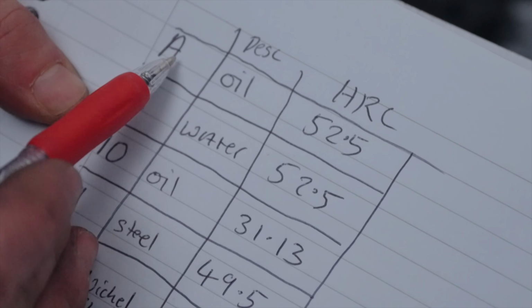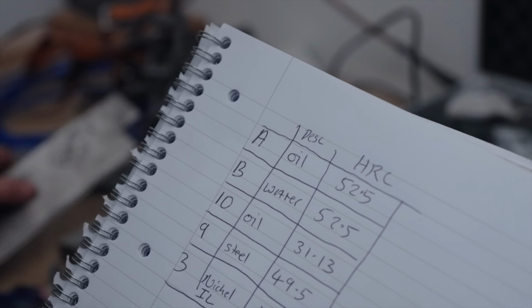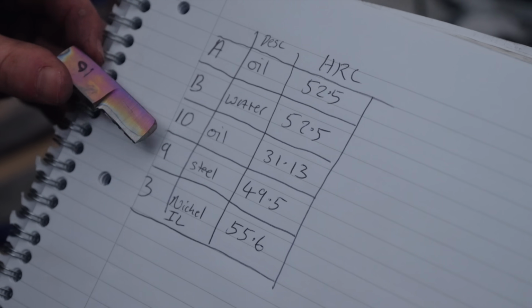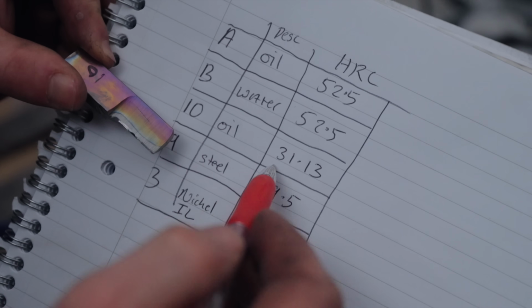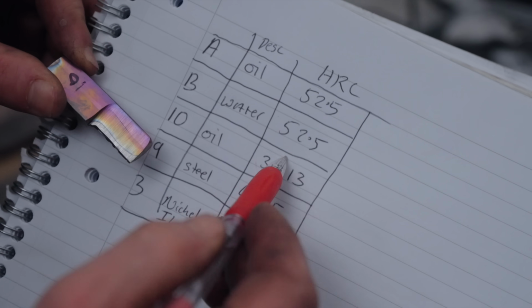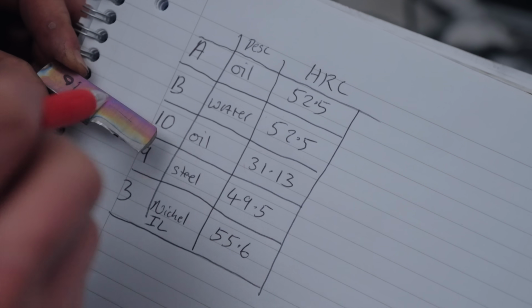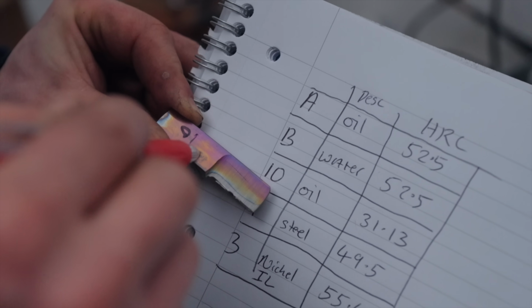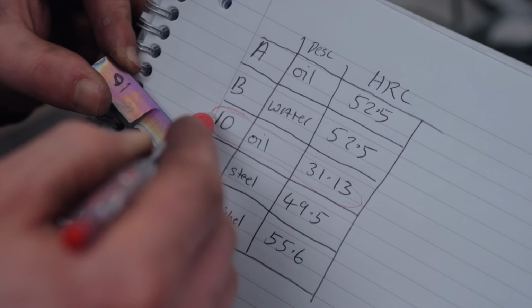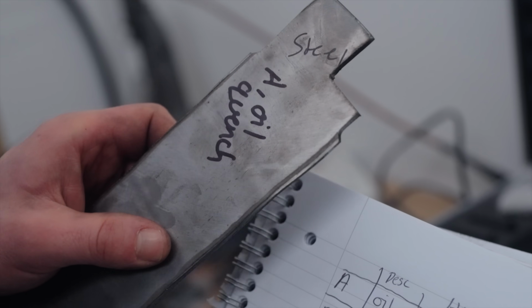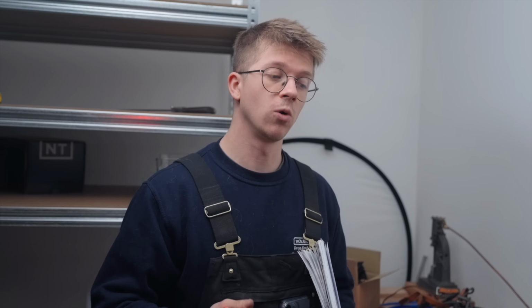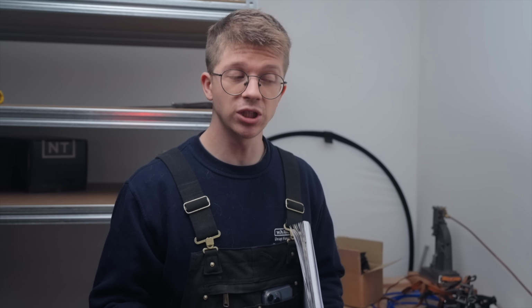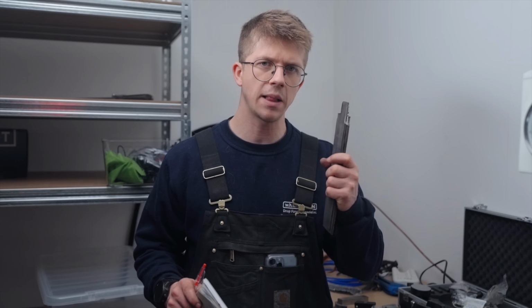Now you would expect that our recent oil test sample would have the same hardness as our oil quench sample from the last set of experiments, but it didn't. It was way harder, and perhaps that's because we had 2 jacketing layers of titanium on sample 10 from the last batch, and only 1 on sample A's oil quench, meaning that the steel core was less insulated and was able to dump the heat quicker. That's my first assumption. But anyway, I would like to see higher Rockwell hardness numbers.